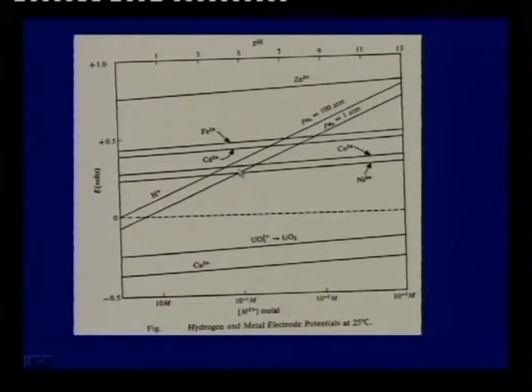And we have shown that while normally nickel ion cannot give nickel metal, if we go to a suitable pH value, or if you apply a suitable pH2 value, the lines for hydrogen ion potential and metal ion potential in the case of nickel and cobalt will cross. Something like zinc metal cannot be produced, no matter what pressure of hydrogen you give or how alkaline it is, because it is far too above in the electrochemical series.